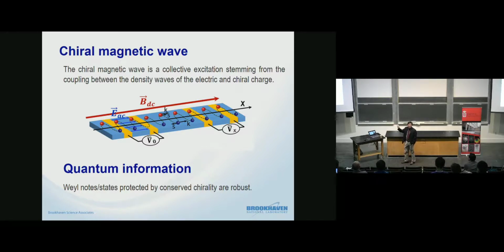Okay, and the most important thing here is that if the frequency of this electric field is high enough and beats the chiral flipping rate, okay, this wave, the chiral magnetic wave, actually could transfer over a much longer distance and without resistance, right? Because the chirality is conserved unless you flip the chirality over there. Okay. So this can provide ways to, I say the Weyl nodes, because they are protected by the conserved chirality. It's quite robust and it could have some use for the delivery of quantum information.